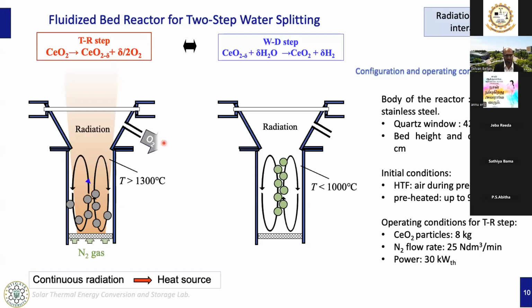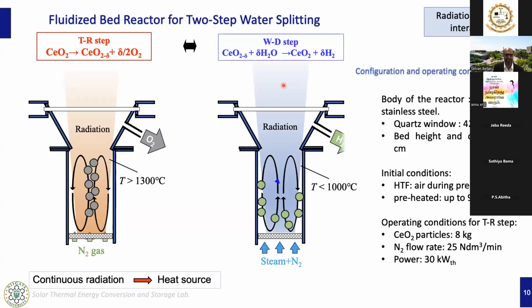And in the same reactor, we usually perform the second step, the water decomposition step. For that, we control the radiation power. We reduce the power and we switch the inlet gas from nitrogen to steam. When the particle temperature is less than 1000 degrees Celsius, this step takes place, and hydrogen is released. So this is the main concept of the reactor. During the first step we produce oxygen, and during the second step we produce hydrogen.